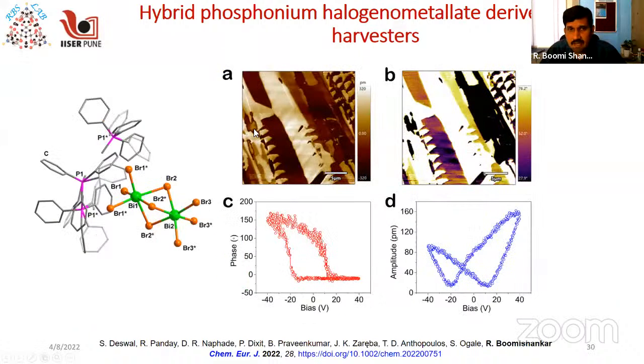And in some cases, we can also visualize the piezoelectric domains using the piezoresponse force microscopy technique, which is nothing but a special AFM technique. In the AFM technique, you can subject the molecule to an external electric field, and then you can visualize the domains. The dark and bright domains indicate domains with different polarization orientations. So this is one orientation, and this will be the opposite orientation.